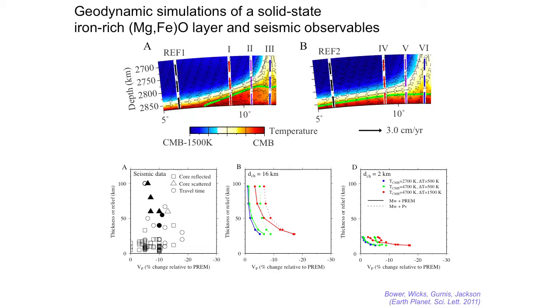Or if we put more of it in, let's say 10% or more, then we get what are more characterized as pancake-like features. And from seismic observations, if we plot all the seismic observations with the thickness of the blob and the P wave reduction, so down to 20%, and we model that with a mixture of perovskite, the coexisting silicate, we see that the seismic observations here can match well with some of these shapes and thicknesses of these blobs, and they're quite stable. So over geologic time, they can stabilize themselves, and they can then be probed by the seismic observation. So they're not transient features. They will likely not go away.